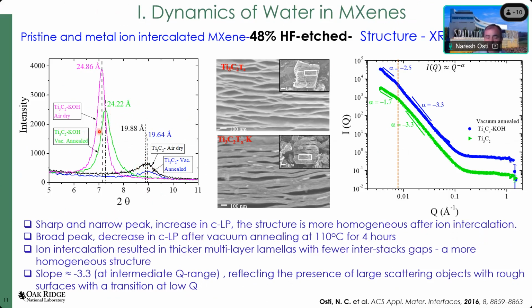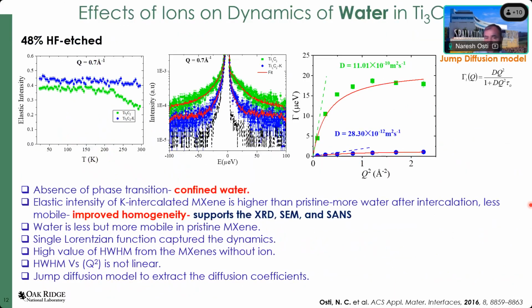It means that the structure becomes much more homogeneous once you intercalate the metal ion between the MXene layers, which is well illustrated in these SEM images as well. That homogeneity in the structure can also be reflected from the slope that you get at the low Q from the small angle neutron scattering technique. Then we move to the dynamic aspect of this study, and at first we collect the elastic intensity data as a function of the temperature.